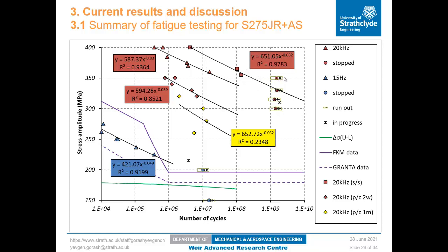There is an obvious fatigue limit for this group of the data, which is found around 350 megapascals. So the next group of the samples are two batches of pre-corroded samples. Purple diamonds are the samples that were pre-corroded for 2 weeks, and yellow diamonds are the samples that were pre-corroded for 1 month. And there is a significant drop of the fatigue life in terms of the stress and in terms of number of cycles. However, there is one run-out sample for 2 weeks, but there is no run-out and no fatigue limit for the group of samples corroded for 1 month.